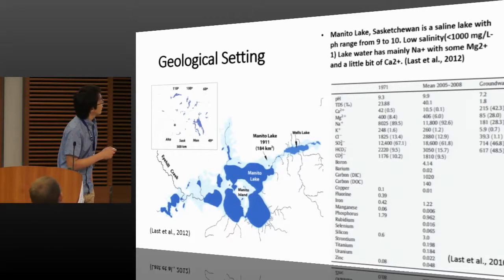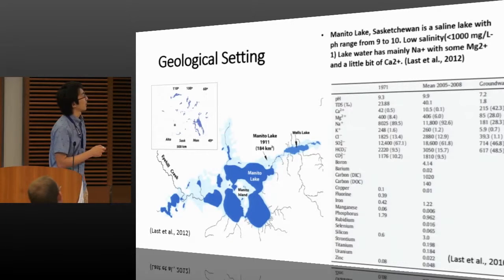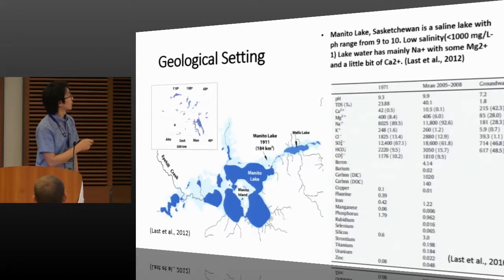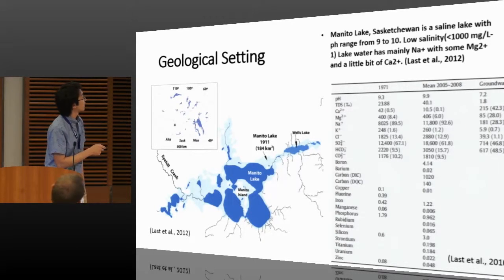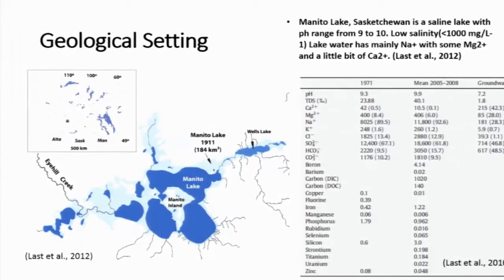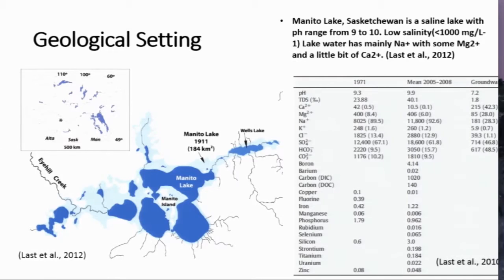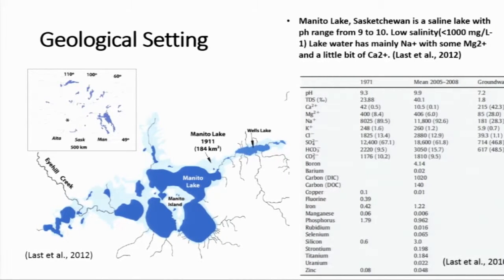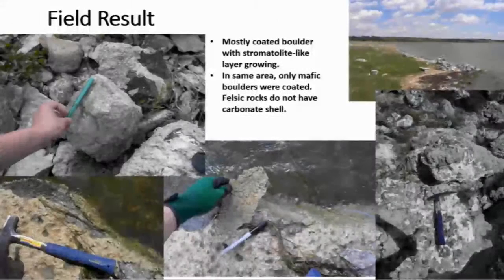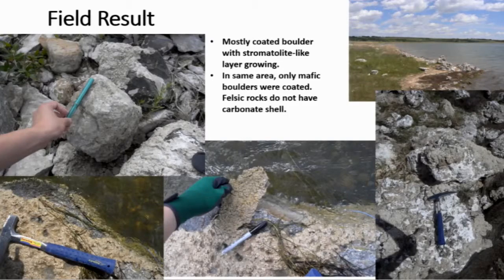And the water level dropped significantly from 1911 to now. So you can see the light blue is the original size of the lake, and it dropped to only about this much now. And because they evaporate a lot of water, the pH increased from 9.3 to close to 10 now. And also the magnesium content in the lake increased. So this is what the field site looks like.